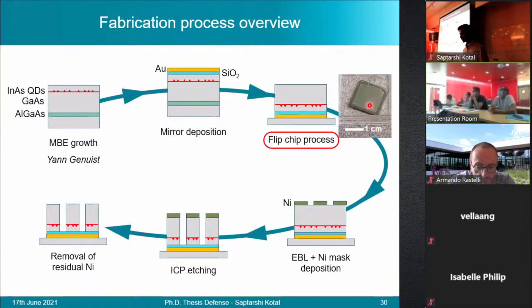During my PhD, I optimized the flip chip process, making it possible to process and develop clean and defect-free membranes repeatedly with an area which is much larger than what was being achieved in the team in the past. The following steps consist of the top-down processes, which involve the electron beam lithography step, then the definition of a nickel hard mask with a lift-off process, and then we put the sample into an inductively coupled plasma chamber to etch it, and thereby defining the nanocavities. The final step is to then get rid of the residue of the nickel hard mask.